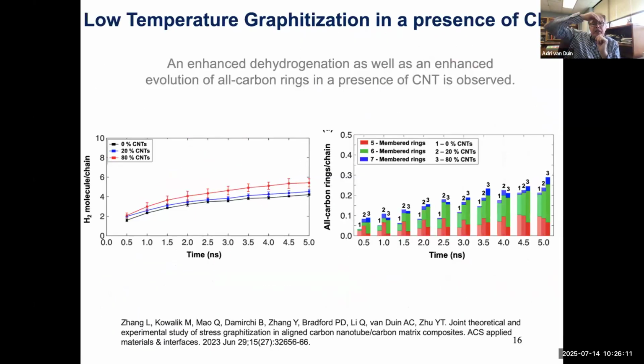And interestingly enough, you can actually direct this process. One interesting thing that you can discover is how additives change this process. A very popular additive that we tried out was carbon nanotubes. And we found indeed that the carbon nanotubes can direct the growth. Without the carbon nanotubes, you get growth in all sorts of directions. It's very hard to control. With the carbon nanotubes in place, we actually can control the growth, and most of the new growth actually happens parallel to the carbon nanotube.